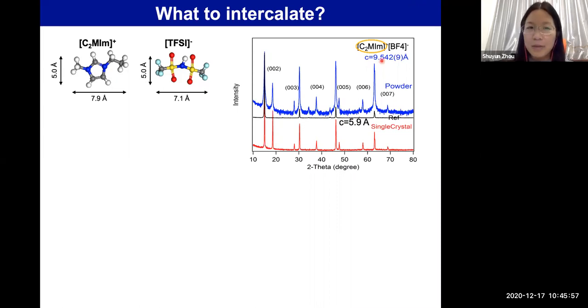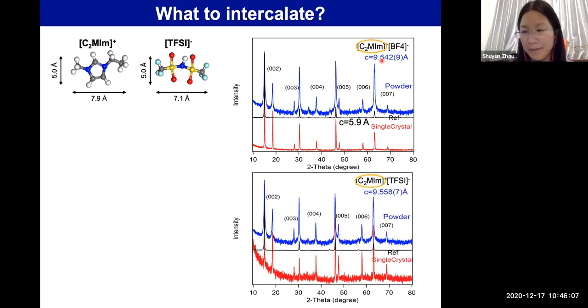We can use different combinations of cations and anions, and from the comparison, we can find out what kind of ions we have intercalated here. So here is the X-ray diffraction pattern using a different ionic liquid with the same cations but different anions. We see that after intercalation, the interlayer spacing remains pretty much the same. So this tells us that the cation is probably the one that is intercalated into the sample.